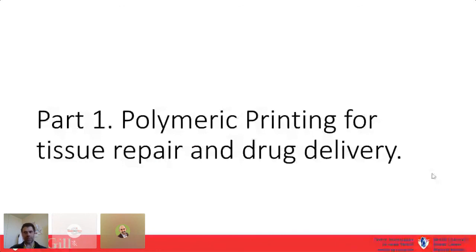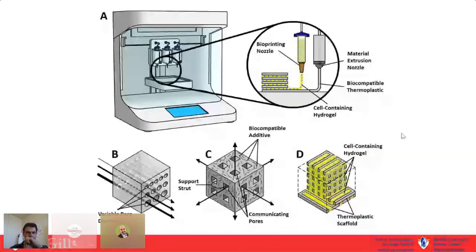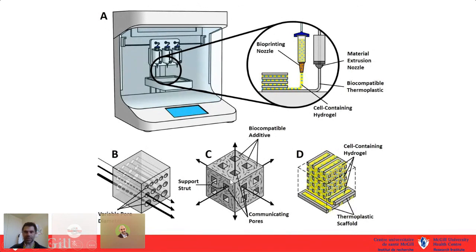This image really shows the different types of things we're doing with 3D printing. With the bioprinter we can have thermoplastic print heads or hydrogels with cells, and we can control pore sizes — which can have a physical effect on stem cell differentiation. We can use thermoplastics with bioactive additives such as calcium phosphate ceramics that have a biochemical impact on stem cell differentiation. We can also co-print thermoplastics as a support structure with an interpenetrating gel network containing cells to create composite structures.